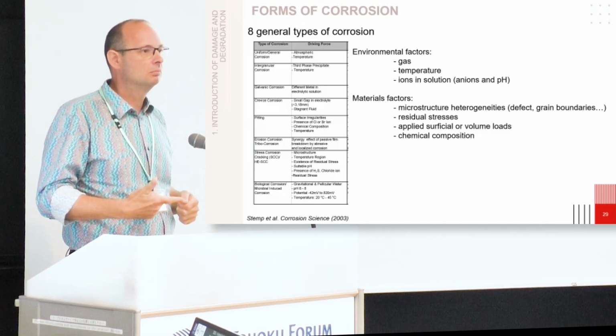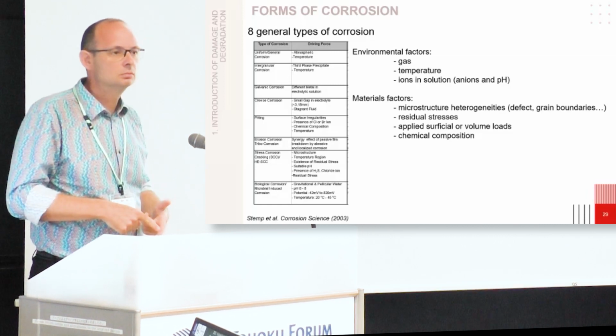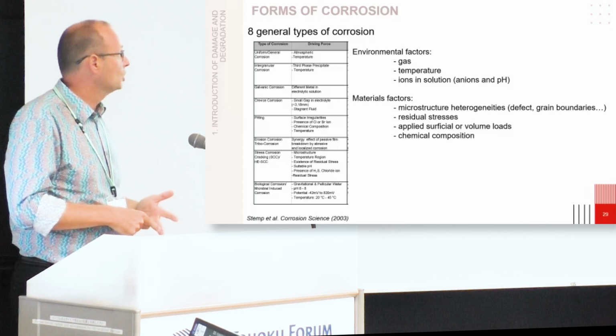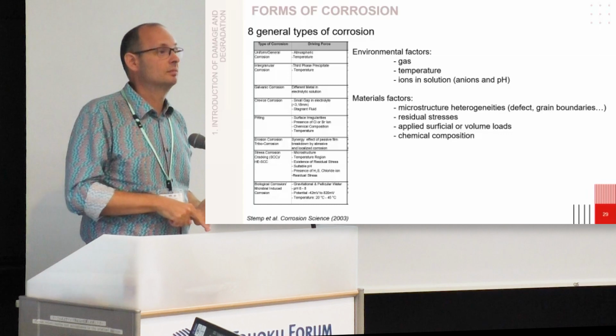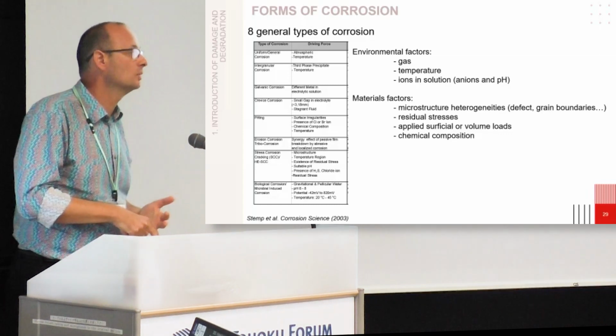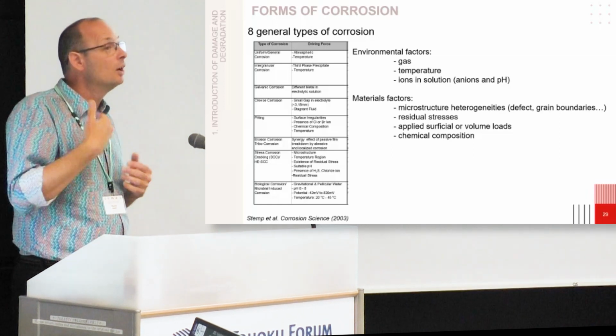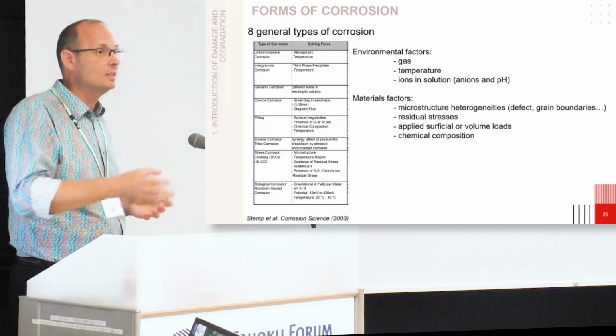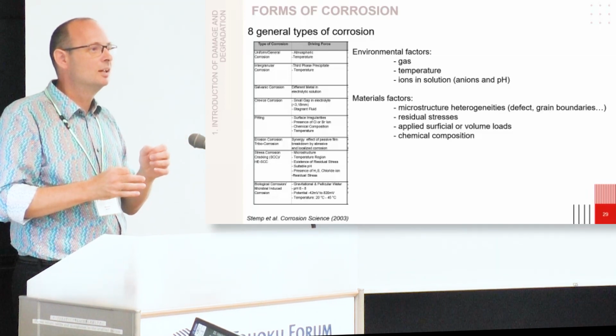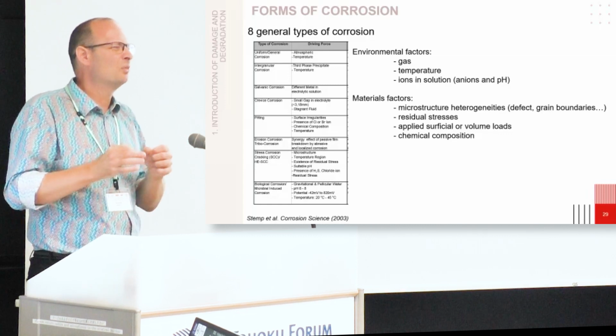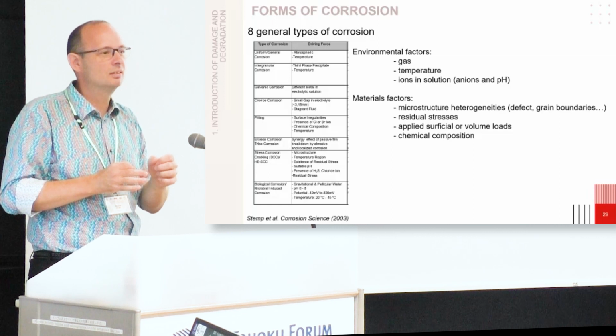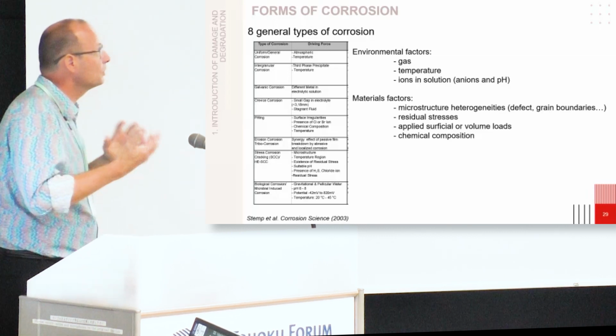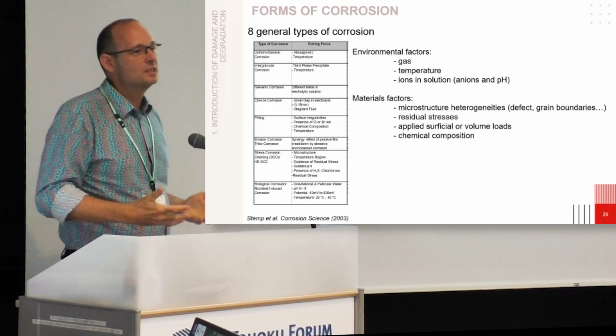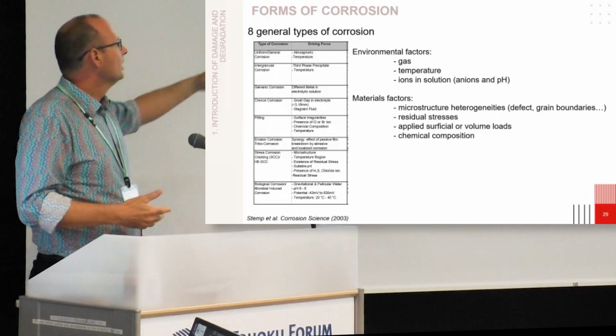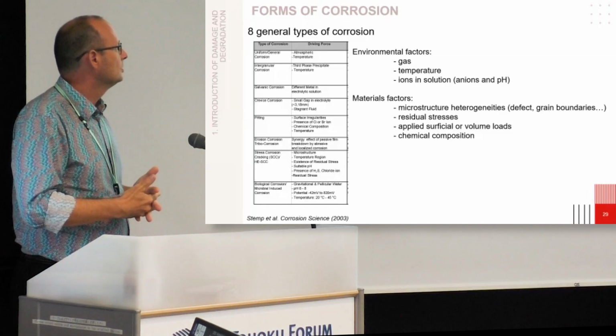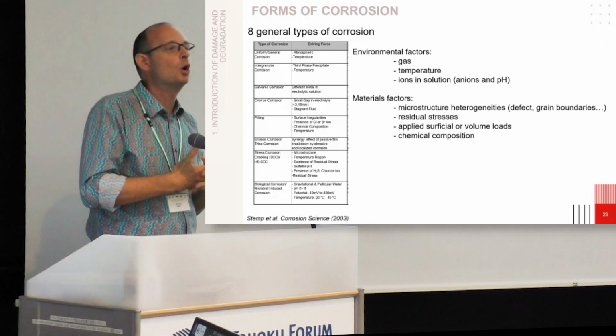So it can be defects, voids, inclusions, heterogeneities, but also grain boundaries. Because you know that in materials, all the grains don't have exactly the same crystallographic orientation. What is a crystallographic orientation? It is a plane of atoms with different densities. Which means different surface energy. Energy, thermodynamics, we restart. So everything is linked. In terms of energy, we also have residual stresses. So that's the first point. And its chemical composition also.